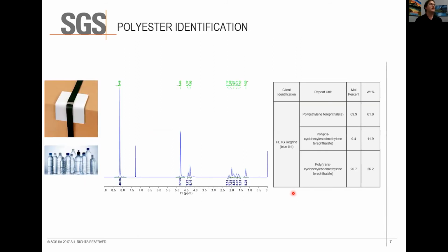Polyesters are another common thing that we do a lot of testing with. Frequently it's just polyethylene terephthalate, and that's real easy to discriminate. Sometimes they get clever and throw in different diols to modify the properties. I don't have a spectrum of it, but the other thing people can do is replace some of the terephthalic acid with isophthalic acid, which gives you a couple extra aromatic signals out there.